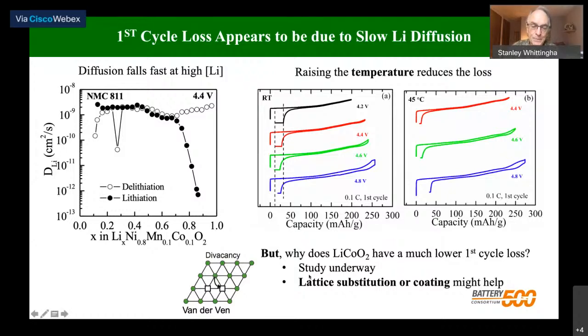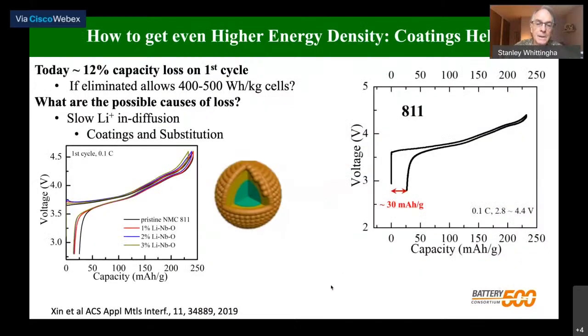There's one slight puzzle in all of this. Lithium cobalt oxide does not show this behavior. Same structure. So we're looking at that. We believe if lithium cobalt oxide doesn't have this problem, then we should be able to modify the structure of the NMCs by either lattice substitution or coating. That should help.